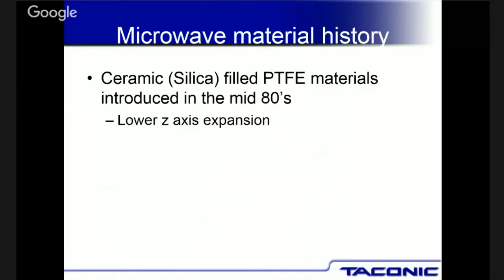What we did in our industry a lot is always trying to figure out how to improve materials. In the mid-80s, a lot of people were complaining about how to build boards, and the Z-axis expansion was so high and the material was moving so much that they couldn't effectively build good boards and get good plated through holes. And so what we found is that by sticking silica, regular pure beach sand, into the material, we could actually change the mechanical properties of the material without changing the electrical properties very much. And so, it's been since the mid-'80s, we've been making these ceramic-filled, silica-filled Teflon materials.